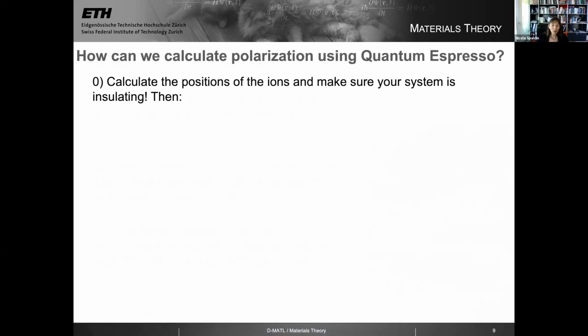Before we go on to use this though, I should tell you practically how, if you want to calculate a polarization using Quantum ESPRESSO or any other electronic structure code, you should go about doing it, so that you have that in your toolbox and can practice with the skills you've been learning the last couple of weeks. So the first thing, if you have a bulk periodic solid and you want to calculate its polarization, is you have to calculate the structure of the solid. You have to calculate the positions of the ions. And what's super important is you have to make sure your system is insulating. If something is metallic, it can't sustain an electric polarization. I'm sure you've been learning this week about, for example, magnetic insulators. These could be rather challenging to achieve insulating behavior in a density functional calculation. So you have to be very careful and make sure that your system is insulating in order to have a sensible definition of polarization.